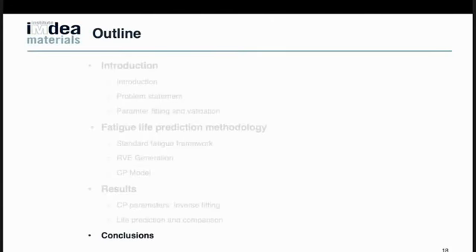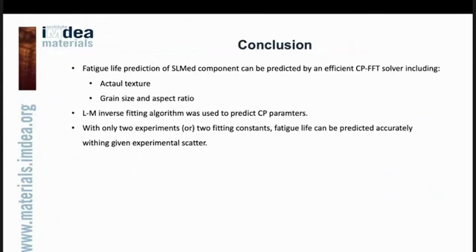Finally, we are able to predict, with all this formulation on the right-hand side, the fatigue life within the given scatter, and we see quite accurate fitting. So the conclusion is that for the SLM component, using the efficient CPFFT solver and homogenization, including actual grain size and actual texture, we are able to predict the fatigue life. Okay, thank you very much.